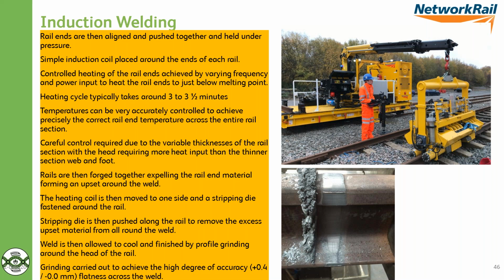They're currently welding up, but at the same time I'm hoping that the technology from Sheffield out on site with them will be able to measure rail stress, and we get both effective welds that we can potentially re-stress. They're also looking at the potential of being able to stress the rail without cutting it. So you can apply the induction welder. It doesn't need two cut ends. You just put the coils on, heat a section of rail, and then forge it together.